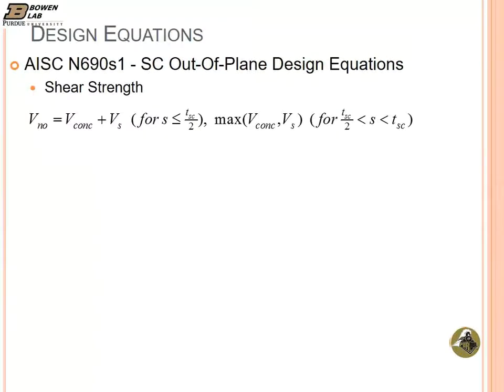Before we discuss the experimental results, I'd like to take a moment and briefly go over the design equations that we have in the AISC code for both shear strength and flexural strength. First, the shear strength equation is shown here. You see it's a similar approach as ACI 349 or 318, the building code, where the shear strength is summed by the contributions from concrete and steel if you have a spacing less than half of the thickness. So you can sum these two contributions if the spacing is less than that level.